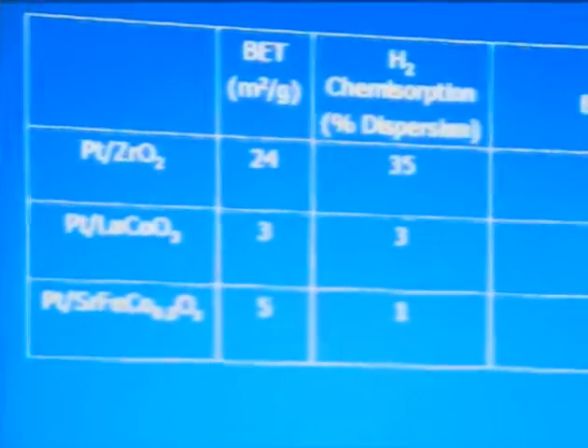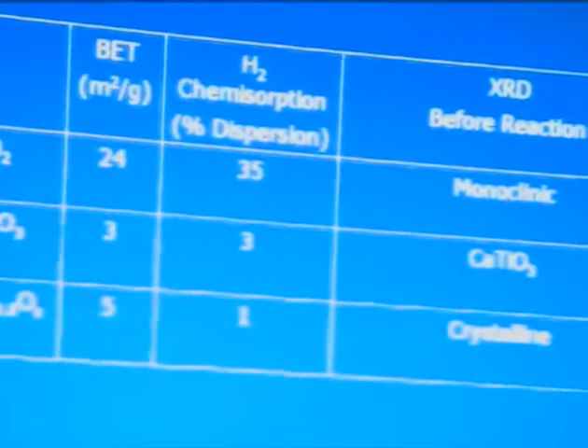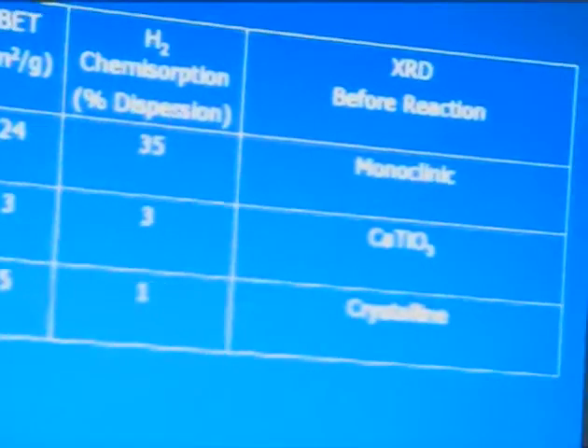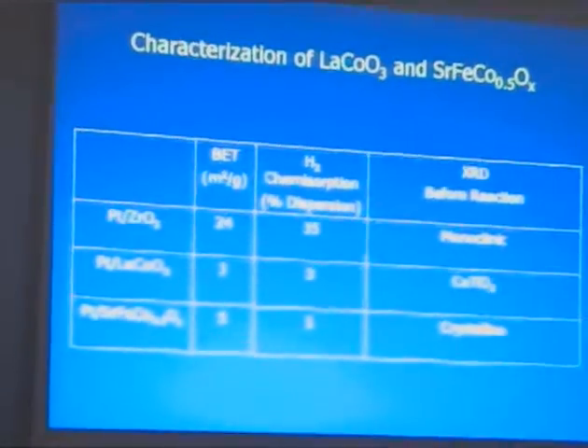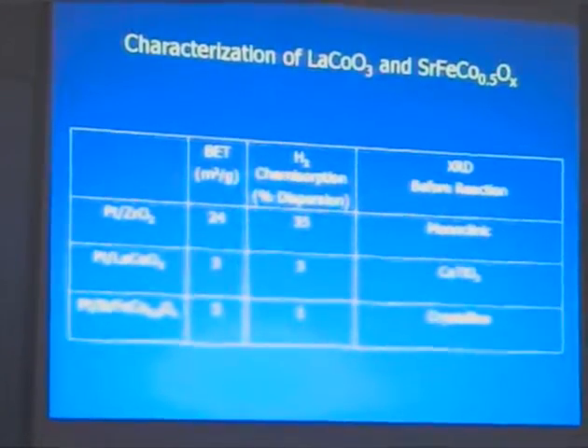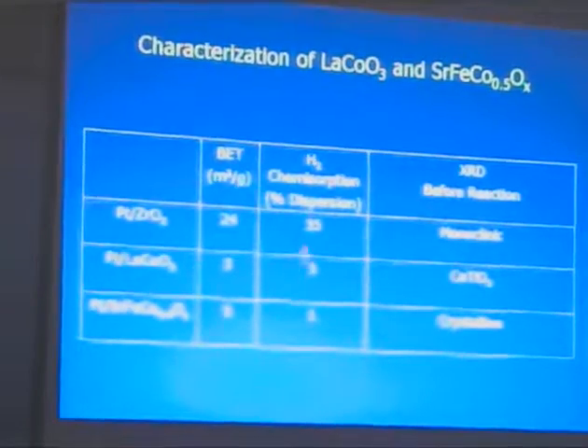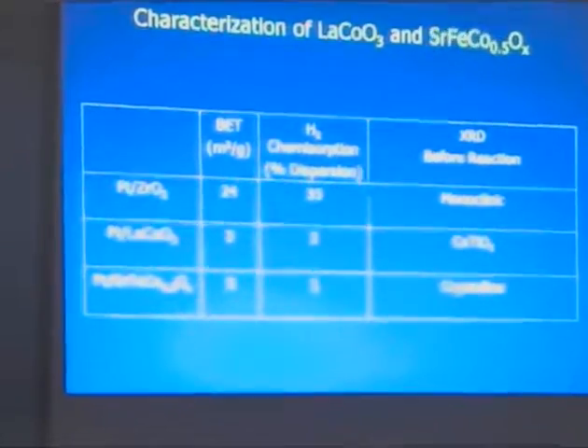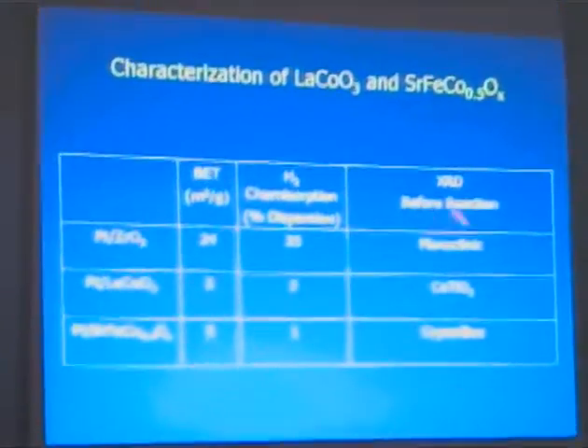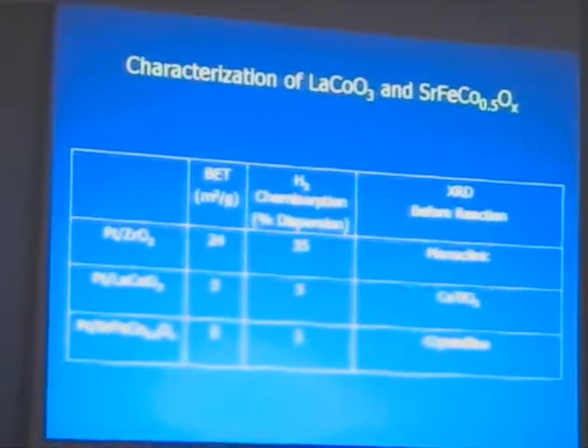When we did the characterization of the lanthanum cobalt oxide and the strontium iron cobalt oxide before reaction, we see with the BETs we had very low surface areas after calcination at 800 degrees. Hydrogen chemisorption was done after reduction and then heating up to 800, followed by low temperature reduction again. And so you can see that our platinum dispersion is very, very low on these materials. X-ray diffraction before reaction, so we had the perovskite structure and we had the crystalline structure associated with this material.